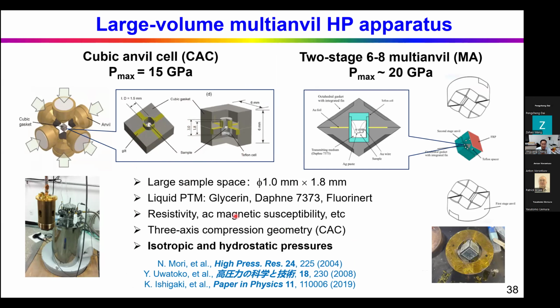So not the diamond anvil cell, which uses a pair of diamonds, so it's a uniaxial compression. Here we use multi-anvil high pressure techniques. One is a cubic anvil cell, which consists of 6 anvils compressing the sample from 3 orthogonal directions. And the 2-stage multi-anvil, or 6/8 multi-anvil, uses 8 anvils to compress the central octahedral pressure medium.